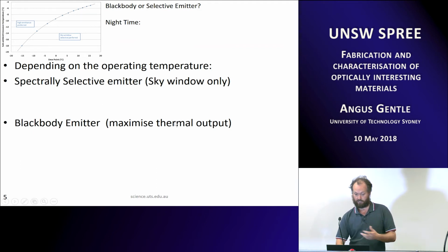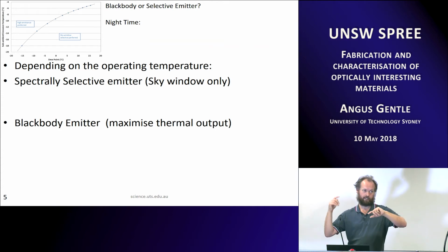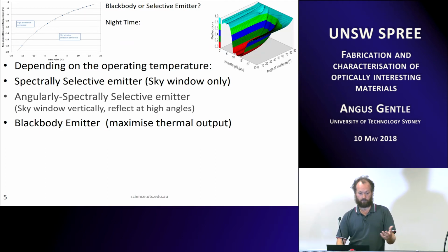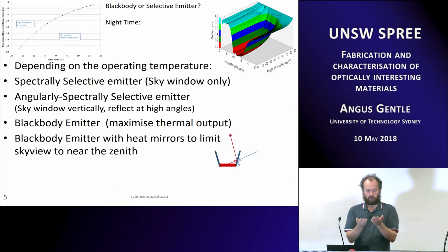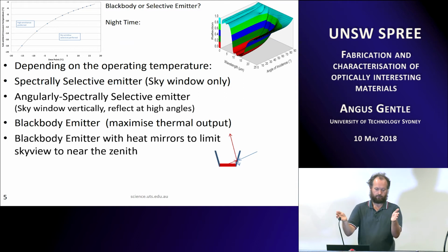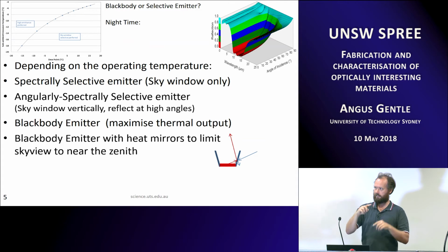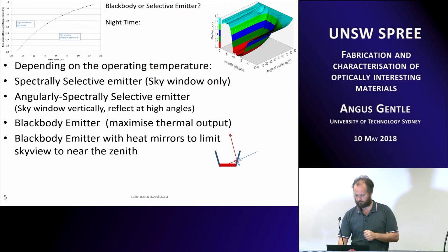So yeah, basically here, a black body emitter maximises the thermal output you can get. So if you're hotter, because it's basically your sigma T to the 4 gets multiplied by emittance. So the hemispherical emittance really matters once you're warm. So the first one I was talking about there was spectrally selective. You can also do spectrally and angularly selective. And then there's another case that you can look at where you've got a black body emitter and then you have a heat mirror on the side. So basically like a silver mirror. So with that, you can emit at all angles, but you only see the sky directly above. So if you end up doing that, you've got the advantage of the black body, but you're also blocking the incoming radiation as well.